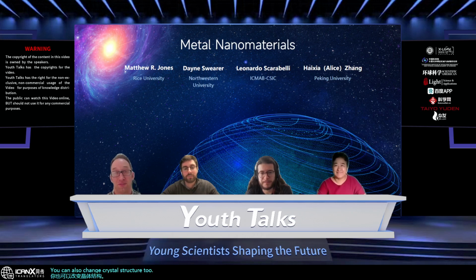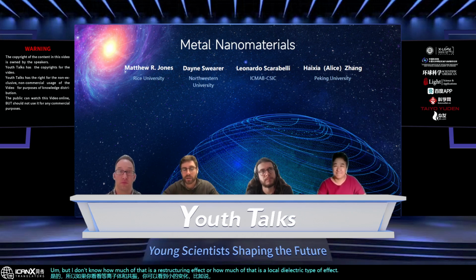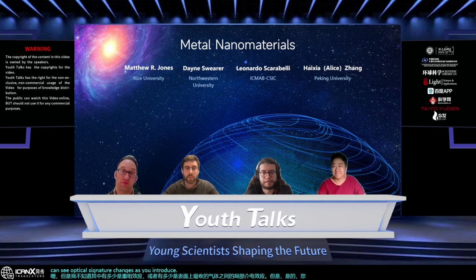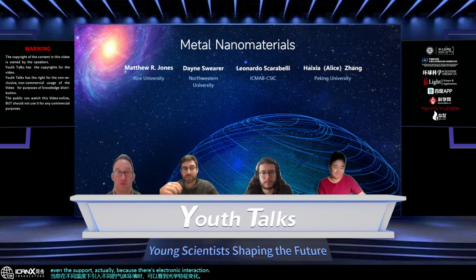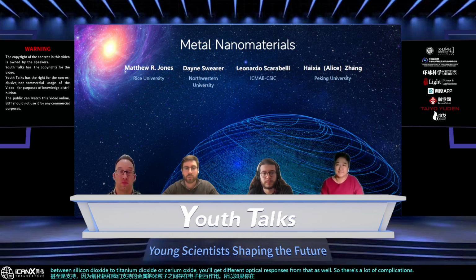Right? And then you should also observe all that in the optical response, right? Yeah, so if you look at the plasmon resonance, you can see small shifts as you introduce, let's say, hydrogen. But I don't know how much of that is a restructuring effect or how much of that is a local dielectric type of effect between adsorbed gases overall on the surface. But yeah, you can see optical signature changes as you introduce different gaseous environments at different temperatures. Even the support, actually, because there's electronic interactions between the aluminum oxide and the metal nanoparticles that we support on. And so if you switch between silicon dioxide to titanium dioxide or cerium oxide, you'll get different optical responses from that as well. So there's a lot of complications in some of these metal nanoparticle catalytic type systems.